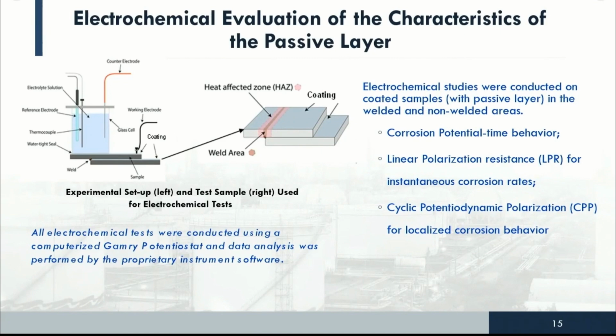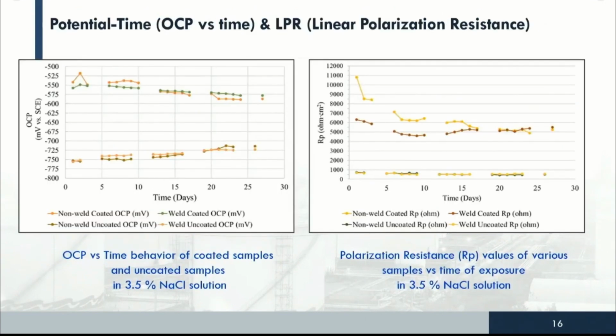We designed a special cell to determine the effect of the weld exactly versus the effect of the non-welded. I'm not going to go into details of the electrochemistry because all of you know it, and we mentioned it in detail in our paper, but I'm going to show you what we have observed from this testing. The first thing we did, we compared the open circuit potential of welded and unwelded bare metal without any coating versus welded and unwelded coated.